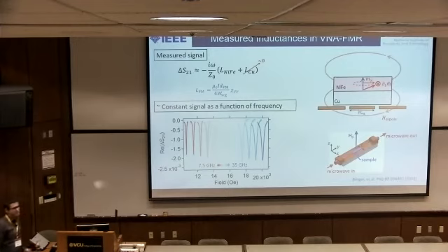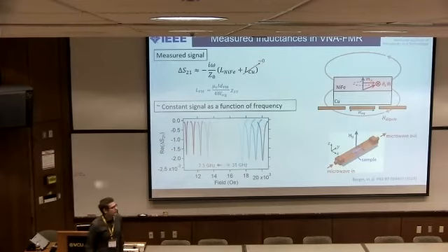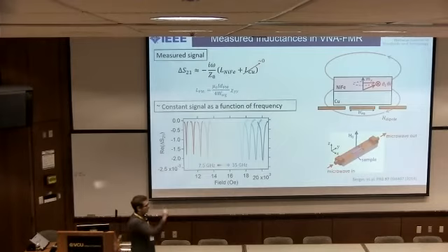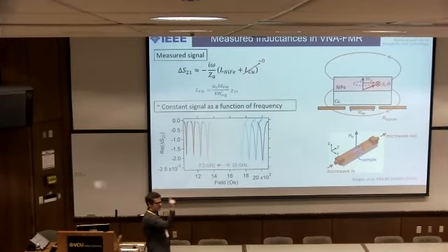So how do we do that? Let's take a closer look at the interaction of our sample and our waveguide. Here's a cross-section of our waveguide. Here's a center conductor. And let's say we have a permalloy bilayer here in contact with a copper layer. This copper has a low spin orbit coupling, so we don't expect any spin orbit torques in this particular case. So we apply a perpendicular magnetic field, set the FMR condition for the permalloy layer, and then we freeze time when the magnetization is in this direction on its precession.